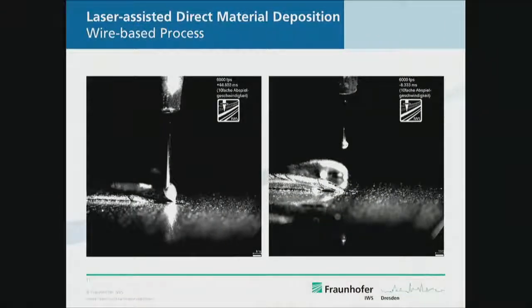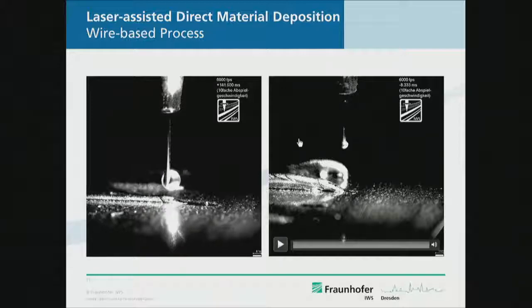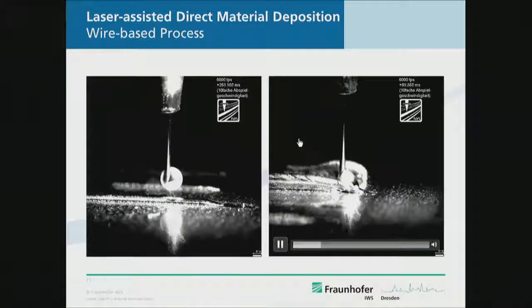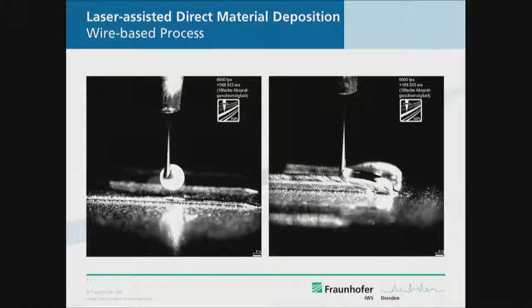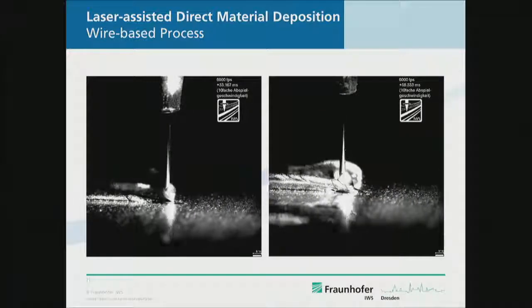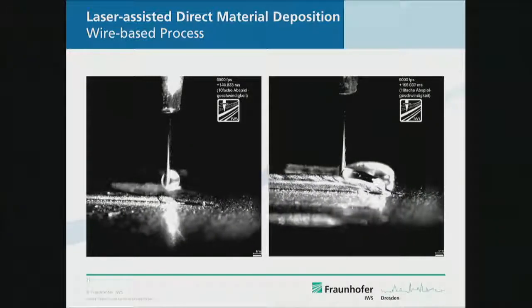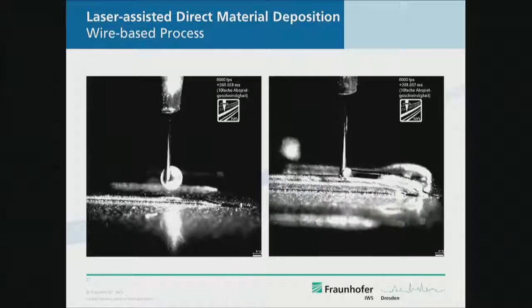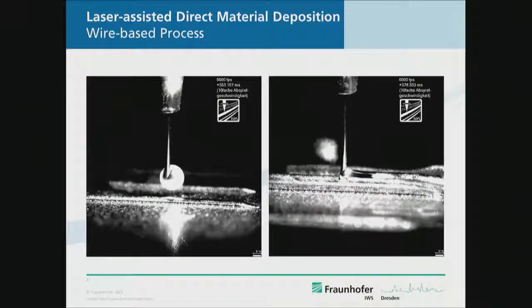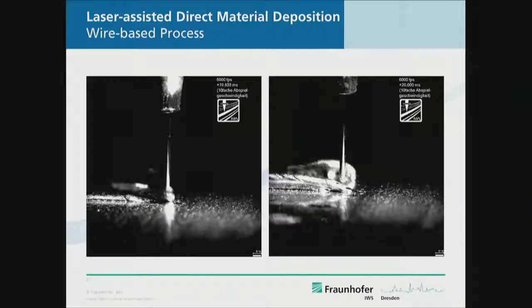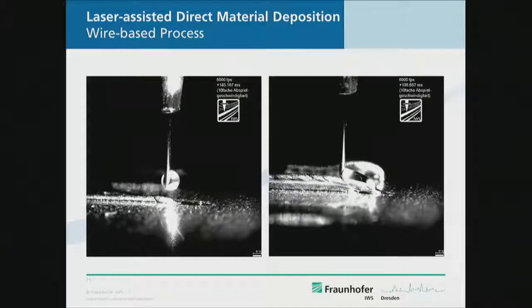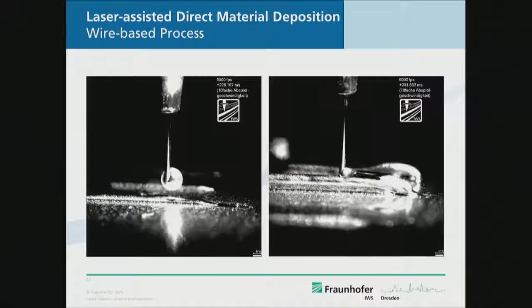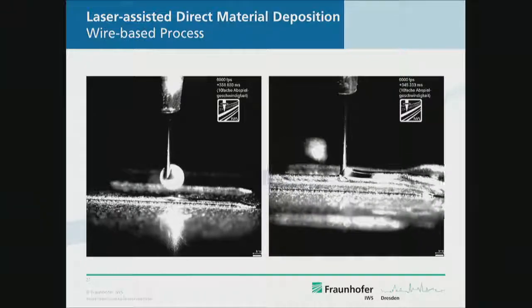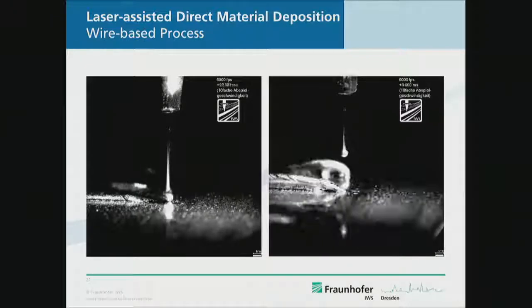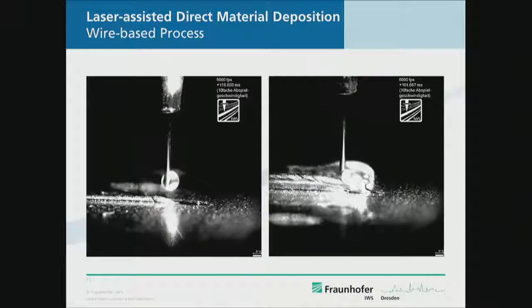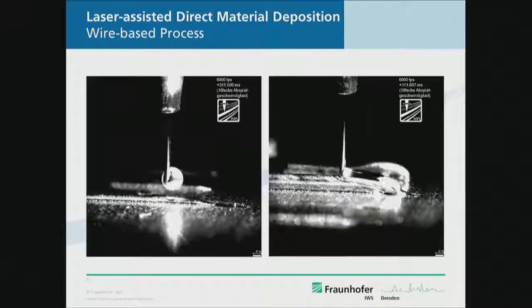This is a high-speed video showing how the wire-based process runs. And as you can certainly see, on the left-hand side, it shows an example of how important knowing about the processing parameters is. Obviously, on the left-hand side, it's a non-optimized process. So the melt bubble sticks to the wire rather than forming a melt pool on the component. On the right-hand side, you see a very smooth process.